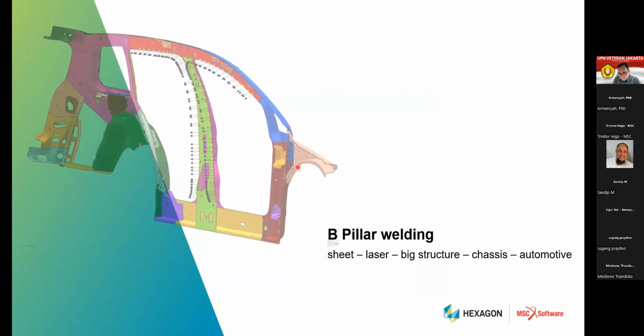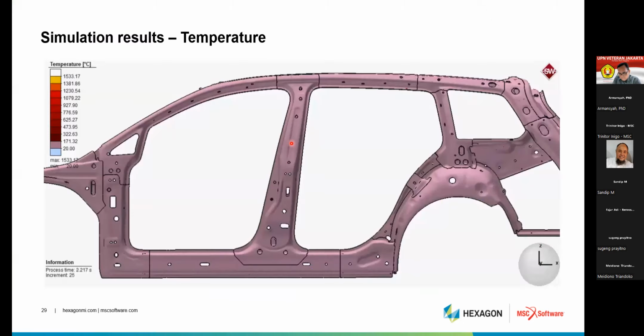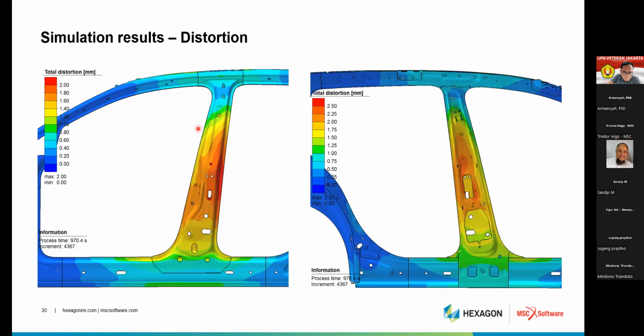Another example is the B pillar welding. In the animation you can see the welding operation happening and this is the temperature result, showing how the temperature is generated during the welding operation. And this is the distortion. This is the area where the high distortion is. You can see that it is about 2 mm here, and this is the back side of it.